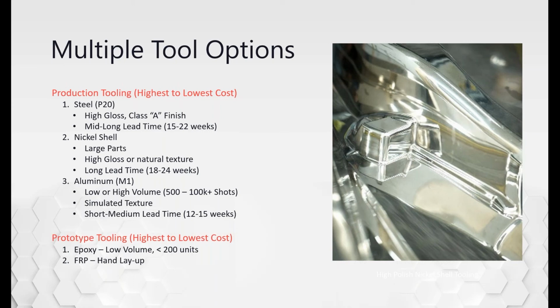So when we do epoxy molds for prototypes, we generally would like to run them once. We'll run them one time, get as many parts as we can, and then move on. Making changes, so if we wanted to move a rib over, if we needed to add some features, changes in the epoxy tools are not real easy to do. The other prototyping method we've used is hand layup FRP or fiberglass, which you don't get any of the B-side details that we're capable of. It's more of a fit representation of the part, not so much a functioning part.